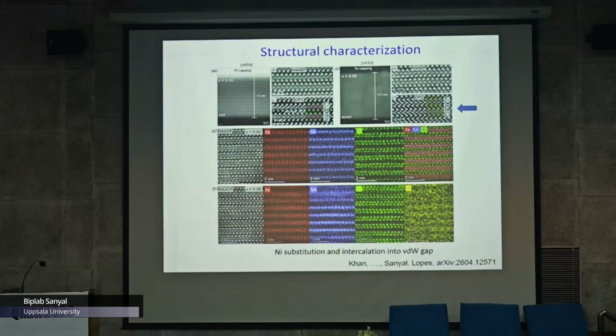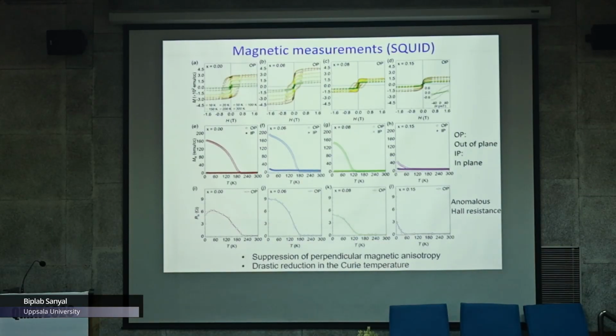And if you go further, they have done several measurements, magnetic measurements, bulk SQUID magnetometry, and also XMCD measurements, synchrotron-based experiments. They show that with a nickel concentration, this is 0%, and then how the out-of-plane magnetization loops change with the nickel concentration. And with the anomalous Hall resistance also, basically two things were concluded.